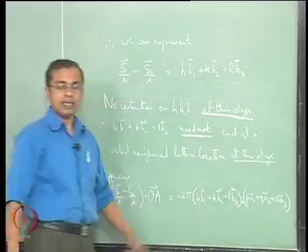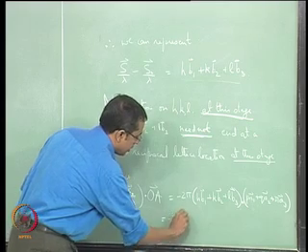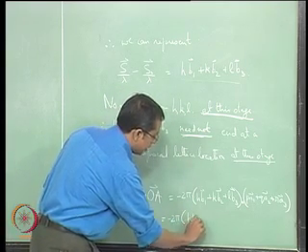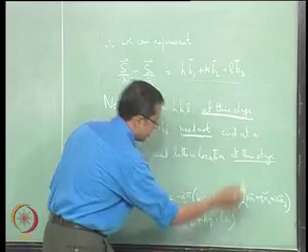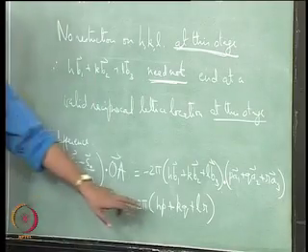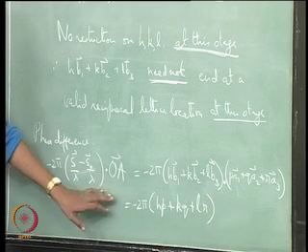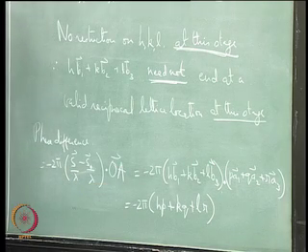to be integers. At the moment H, K and L could be anything, they need not be integers. So if you do take the dot product, this is equal to minus 2 pi times HP plus KQ plus LR, this is what we get, of which P, Q and R are integers, H, K and L could be anything. Now for constructive interference, we have this phase difference.